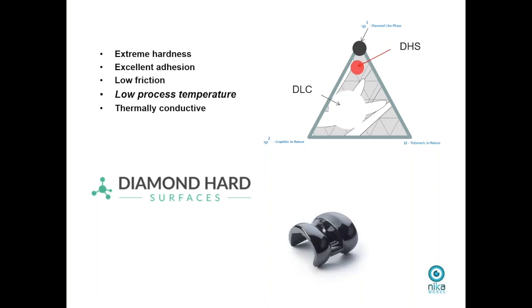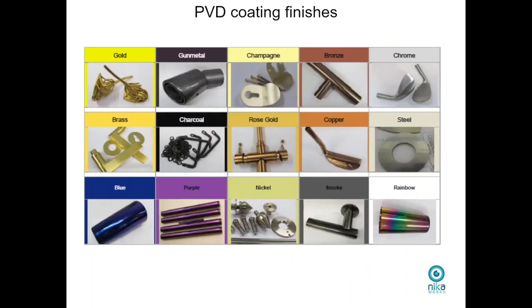On the right-hand side of this slide, there's a triangle. I've taken out most of the detail, but essentially, bottom left is sp2, that's more graphitic-like material. The black spot at the top is where, in a phase diagram, you get much more towards a diamond-like coating. sp3 is diamond. Typical DLC is the white circle at the bottom, and the red circle is where we are with Diamond Hard Surfaces material. So we can see potential applications for that, and I'll describe later on how we're going to achieve that.